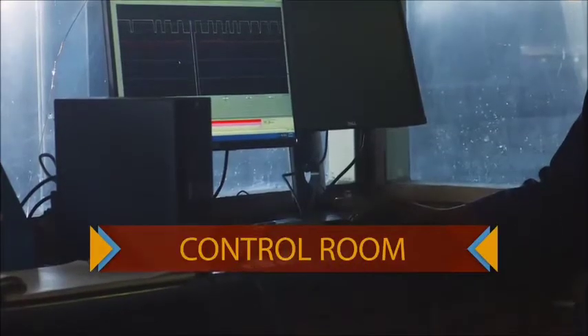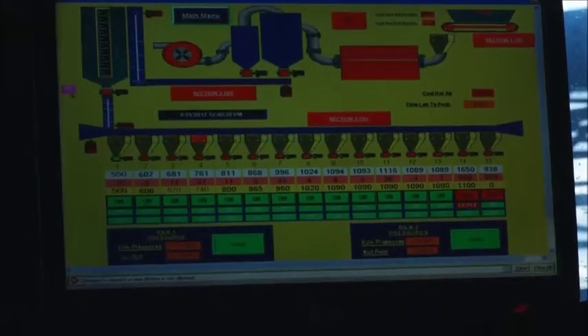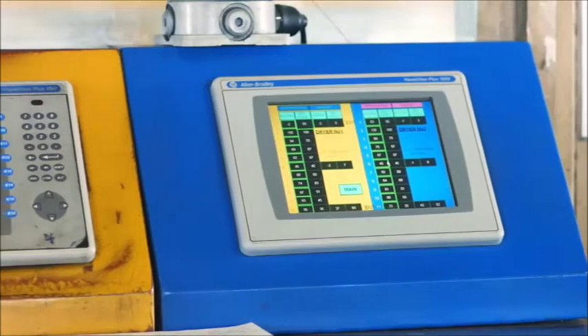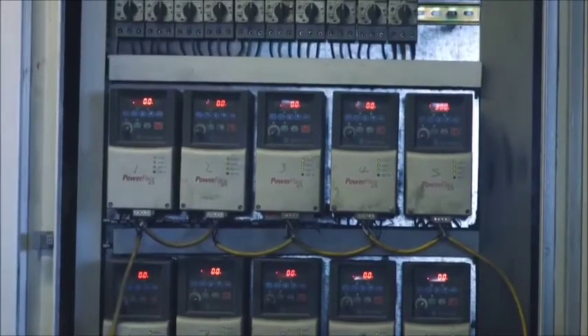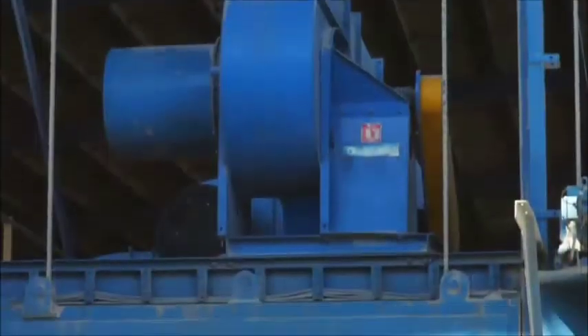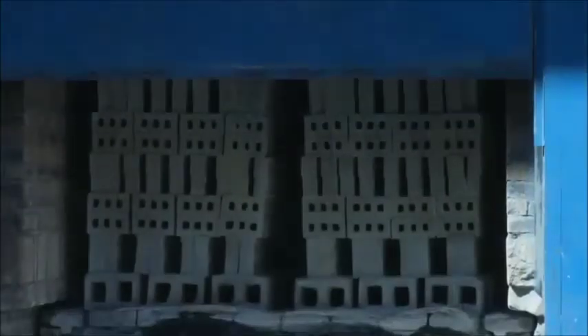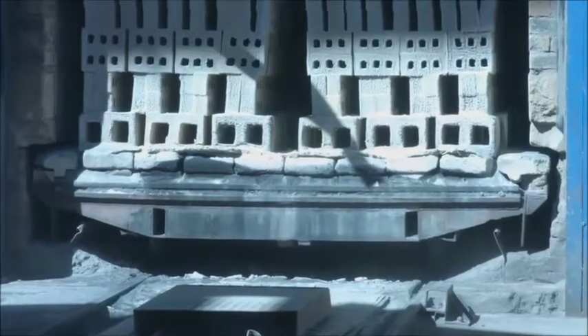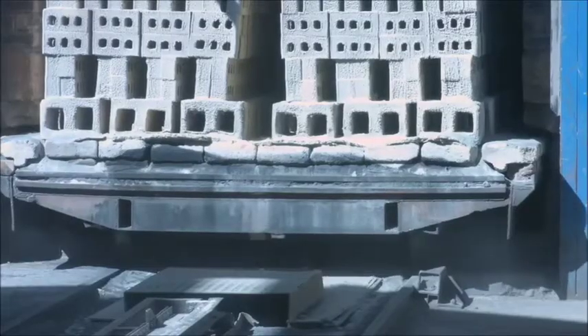This is the control room, where the temperatures for the dryers and the kilns are controlled. The product gets monitored as it travels through the dryer and through the kiln. All the fuel used to burn the bricks is from coal, which is received from Morupule — that's the only raw material imported here for brick making. The bricks go into the kiln from the dryer at 130 degrees, and the temperature in each kiln reaches a whopping 1,120 degrees.